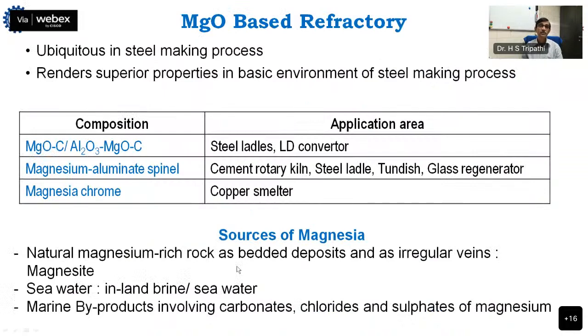So this MgO-based refractory is unavoidable. Without magnesia refractory, steel cannot be produced in the LD. It renders superior properties in the basic environment of the steelmaking process, particularly in the LD. Magnesia carbon and alumina magnesia carbon are used in steel ladles and LD converters. Magnesium aluminate spinel is used in cement rotary kilns, steel ladles, tundishes, glass regenerators, and magnesia chrome.